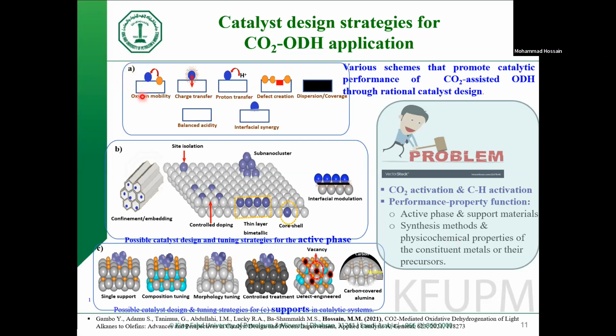So here, in the first figure, one can consider different approaches for designing the catalyst. The first one is adjusting the oxygen mobility, by changing the charge transfer, proton transfer, creating defects, and of course playing with the dispersion, balancing acidity, and also interfacial synergy. The second type shows the isolation of active sites, and there are different approaches for doing it. In the first one, it shows the deposition of the active site inside the channel of a support.